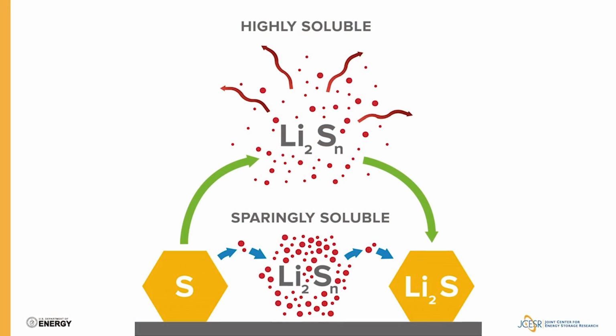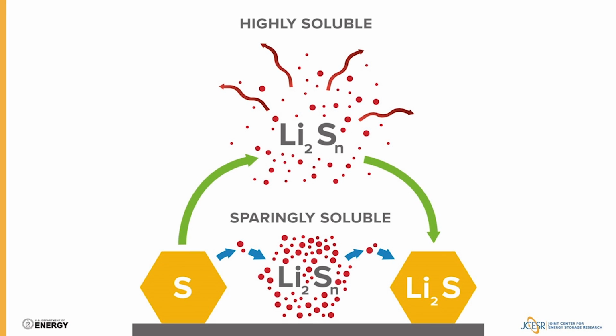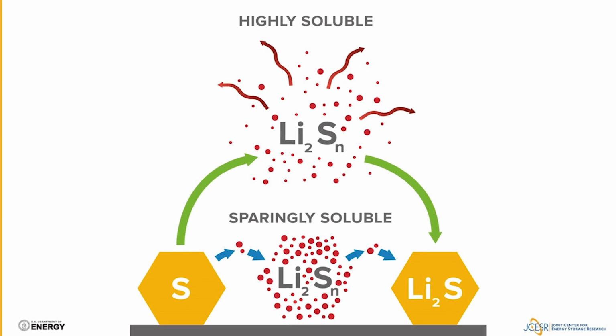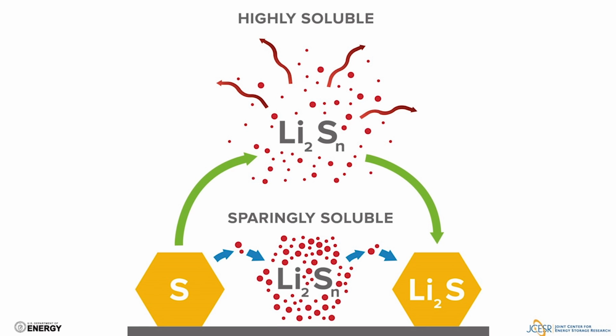So why would one want to use a sparingly solvating electrolyte? Well, for two main reasons. The first is, in the solid state, you always have intrinsically higher charge density, and that directly translates to a higher energy density than you would if you fully dissolved your reactant intermediates. Secondly, with the low solubility of polysulfides in the electrolyte, you are inherently controlling polysulfide migration, the so-called shuttle effect.